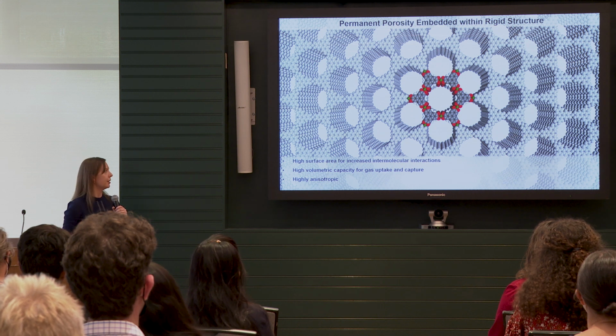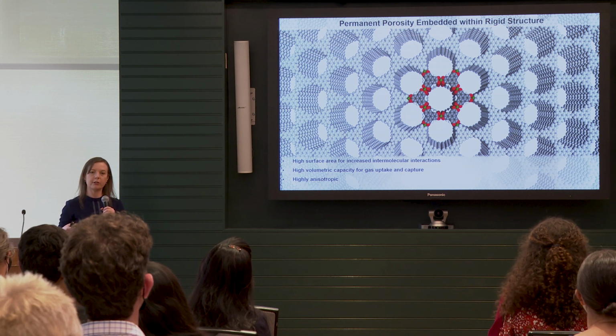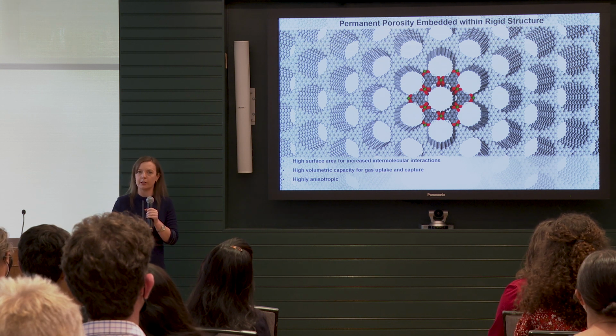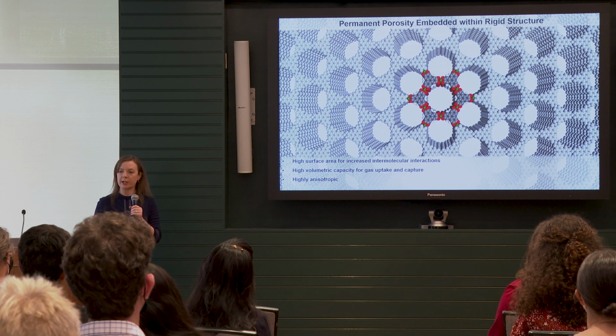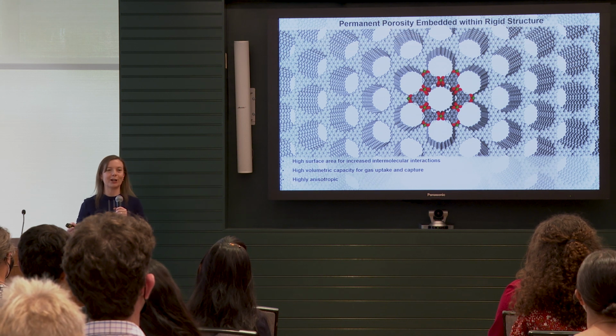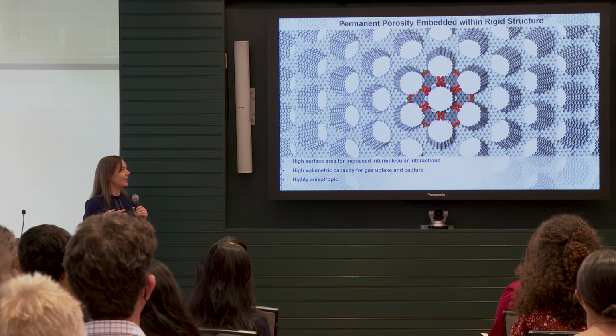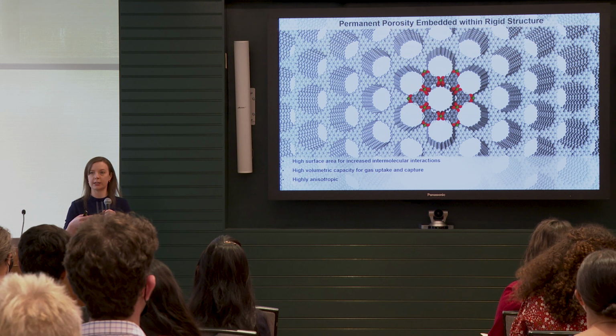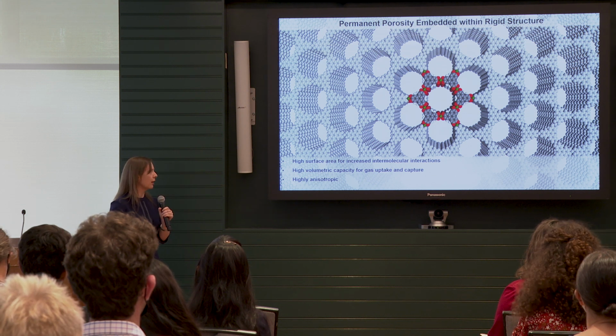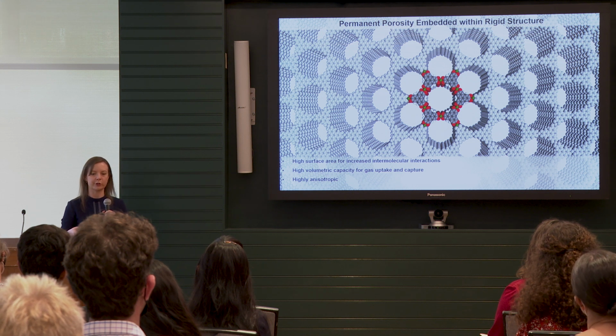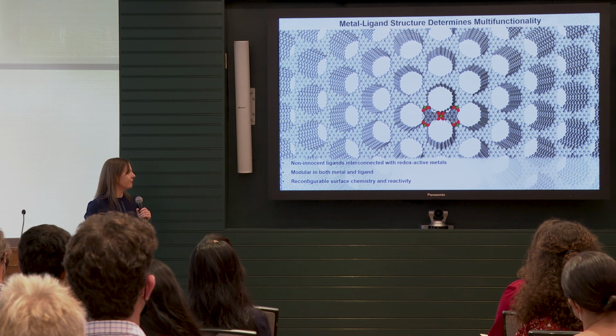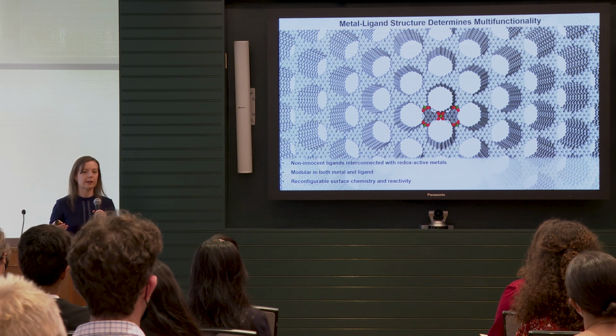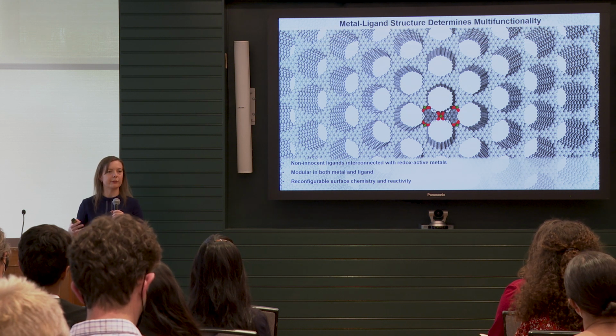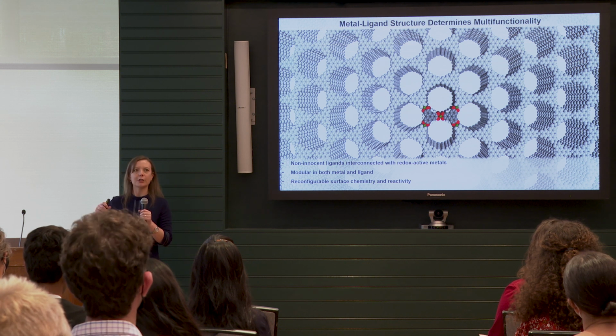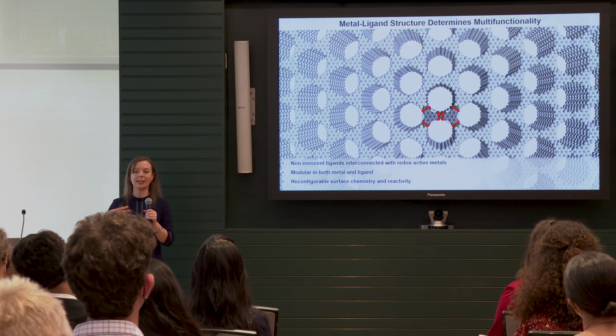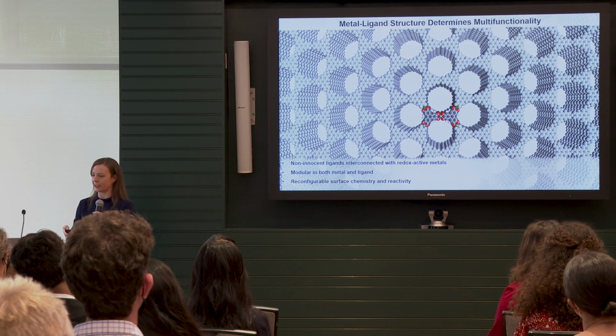We also have, by design here, high surface area of this material, so a large exposed surface area, and that's really good for promoting chemical interactions with the analytes. We have high volumetric capacity for gas uptake, which is great because we're trying to sense gases. And that is a virtue of this material being porous, where the porosity is also built in by design from the design of the building blocks. And then the material is highly anisotropic, and that could be useful for tuning sensitivity and selectivity in the realm of sensing. And then finally, on the molecular level, we have some redox activity in this material, so oxidation, reduction types of events that can lead to reconfigurability of the surface. So lots of knobs to tune and dial in and obtain really unique multifunctional performance that we're really excited about.